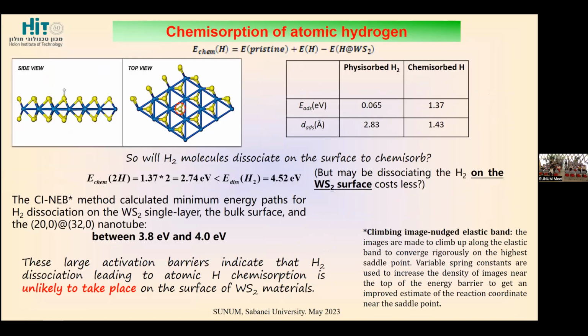But we always considered that atomic hydrogen may absorb better than molecular hydrogen. And the calculations show that indeed absorption of atomic hydrogen is much more beneficial. We have very positive energies. There is, however, one problem. We don't have any bottle of atomic hydrogen. We have molecular hydrogen; you cannot find a bottle of atomic hydrogen because it's not stable. And then you have to pay a lot of energy to dissociate this hydrogen. It's 4.5 eV on the surface. It's slightly lower, 3.8 eV, and still in total, in net, you pay more than you get. So if you already have some atomic hydrogen, it's very useful. But if not, the process is not so beneficial, though plasma process may contribute to it largely.